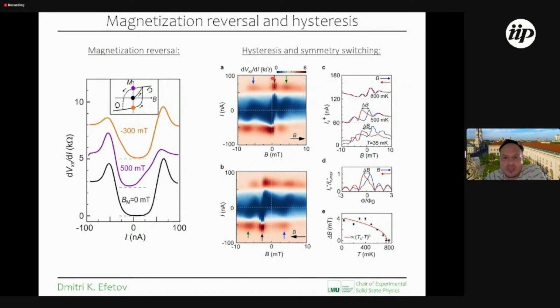And the other thing is, of course, we took these hysteresis maps. So basically, we took the Fraunhofer sweeping only in the up direction and the Fraunhofer sweeping only in the down direction. You can really clearly see between the two color plots here that there is a phase jump between the two curves. And by taking line cuts and comparing them as a function of sweeping up and down, we can see that there is a clear phase shift developing below 800 millikelvin, which is getting stronger with decreasing temperature. So from this phase shift, we can